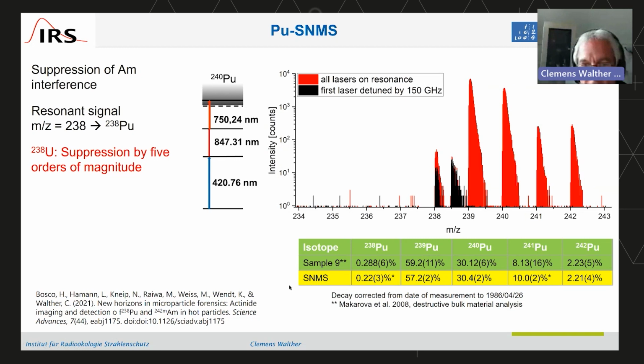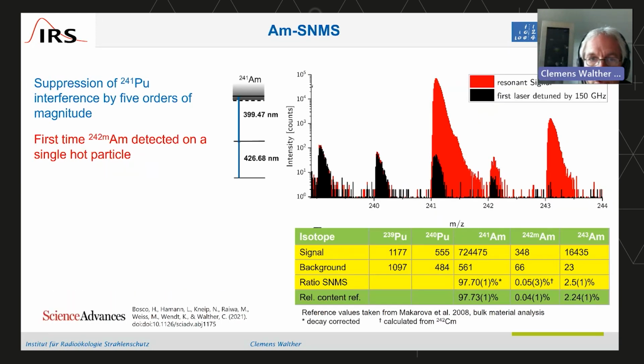And just to know that we are on the safe side here, in this case we knew what the sample should be. Just compare what we find out with the SNMS and what was done on a macroscopic amount of sample. That was done on a sample amount of grams, and we did it on a particle just a few microns in diameter, and that agrees pretty nicely, even for that very hard to measure plutonium-238.